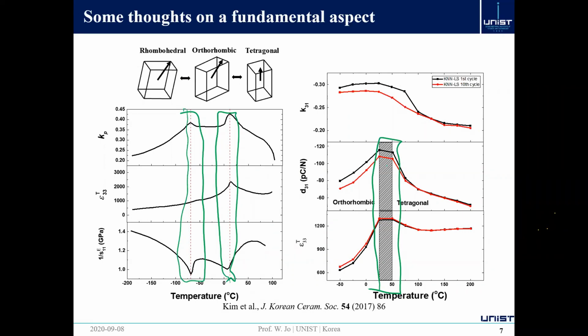But in the meantime, it's really harmful for practical applications because whenever you go across this boundary, you start to lose piezoelectric properties because the phase transformation changes the stable spontaneous polarization direction. That means once the crystal structure is changing, some part of the spontaneous polarization is lost. That's why you start to lose the piezoelectric properties. Degradation happens. So whenever people try to develop new piezoelectric compositions, they always talk about high TC.